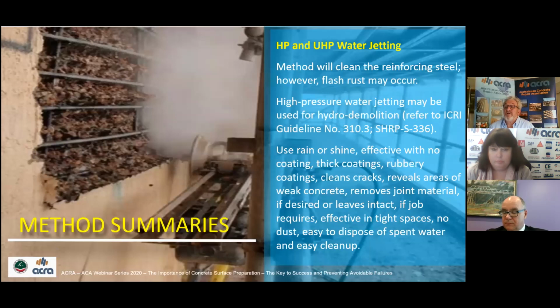The method will clean the reinforcing steel. However, flash rust may occur. High pressure water may also be used for hydro demolition, and that's referred to in the ICRI guideline 310.3. The advantage of ultra high pressure is you can use it, rain or shine. Yes, they're going to get wet anyway, probably.